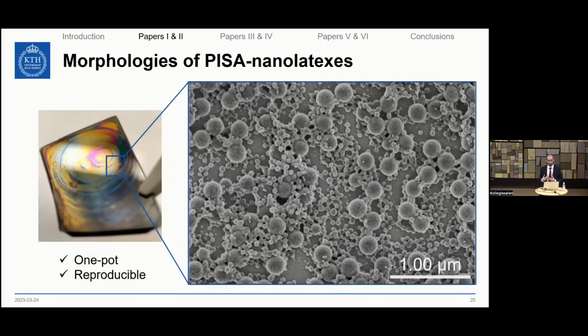So in order to demonstrate the advantages of such a reproducible feature, we adsorbed these bimodal nanolatexes onto silica wafers, and we evaporated the water in order to create these iridescent and opal-like structures, which result from the difference in size. As you can see, we have large and small nanolatexes coexisting, and because of their arrangement on the surface as well. So in the literature, you can obtain exactly the same feature only by mixing two differently monodispersed nanolatex dispersions at different ratios. But we were able to do so by a single pot reaction.